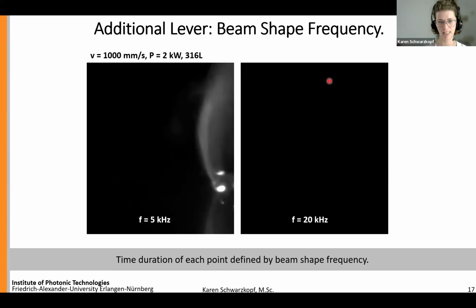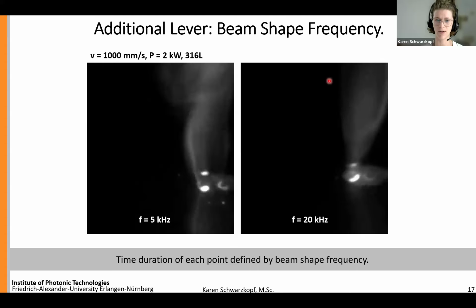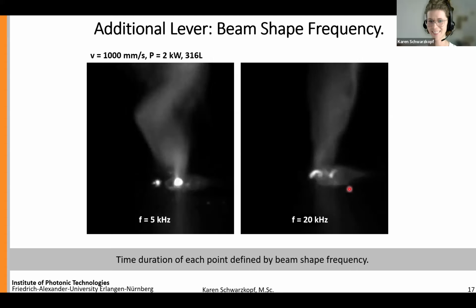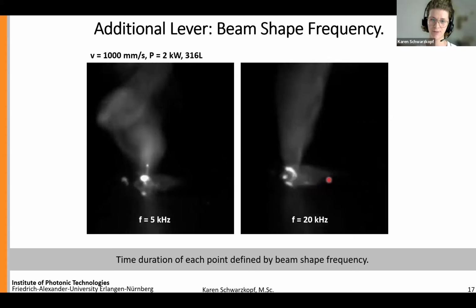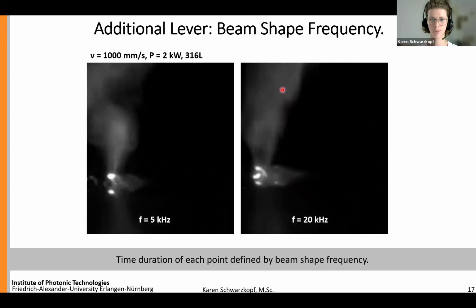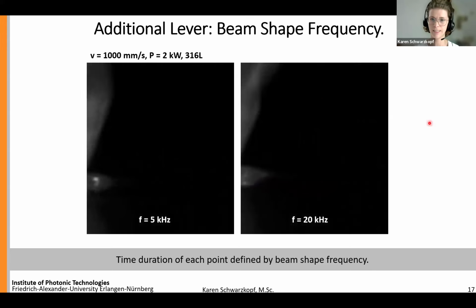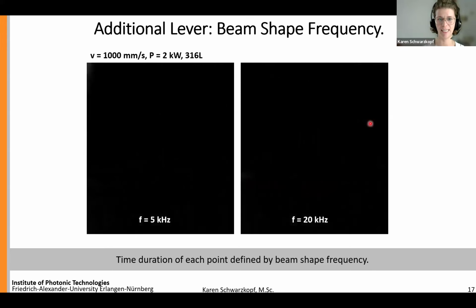So on the left side, you can see a video that is created with a spiral beam shape at a 5 kilohertz beam shape frequency. And on the right side, you can see a spiral, the same intensity distribution, working with a 20 kilohertz frequency. And what is now happening is, you can see that the melt pool is really differing, and not only the melt pool, but also the evaporation. And I don't want to go into detail here. This will be part of the very last slides, because in this presentation, I want to focus on the beam shape frequency.